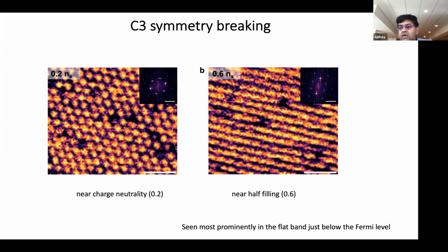Okay. Thank you. So would it be correct to say that you're sitting at one place in the sample, and then as you tune the gate voltage you see how the C3 symmetry is first preserved and then spontaneously broken? That's exactly right. This is in fact in the same area of the sample. And you can see here nice, round things that look threefold symmetric, and here that threefold symmetry is broken. So everything is the same, disorder is the same, nothing else is changed. It's just the gate that's being changed.